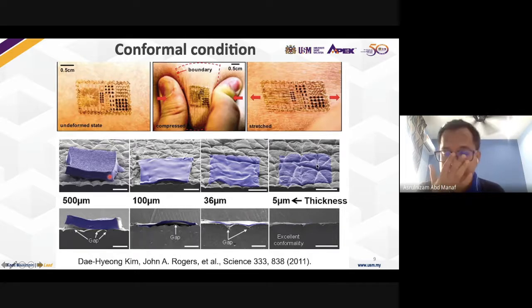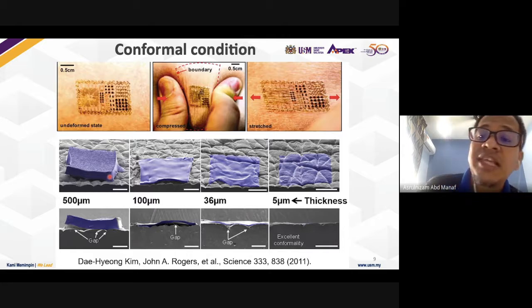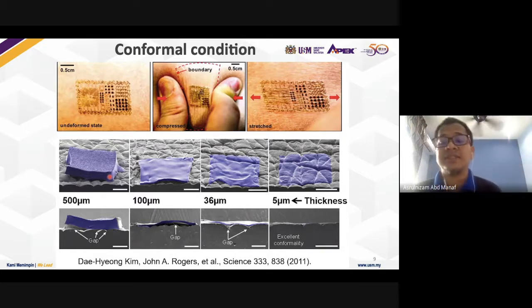But right now the latest thickness was achieved by the group from Yamaguchi University. They presented a 1 micrometer thickness substrate, and on top of that they have an array of OTFT transistors. So this is 2011. And the other criterion is that if you want it to be more sensitive and make good conformance on your skin, the selection of the substrate is not only about being flexible or stretchable, but also about the thickness of the substrate.